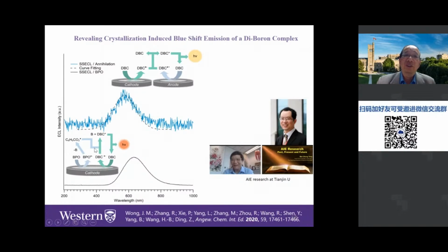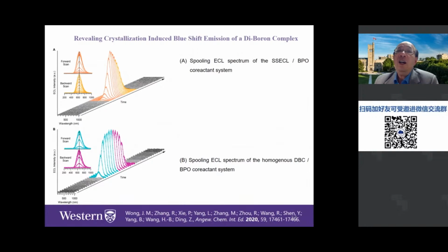I'm going to explain to you what's going on. So in fact, if there's some restriction, that means by this kind of packing of the crystal, you will get the packing, and then you enhance this kind of HOMO-LUMO gap, and then you get blue shifting. And this was proved by DFT calculation. And in fact, if you just get a solution, you don't have the RIR, so then you get kind of red shifted. Right? So that's the thing.